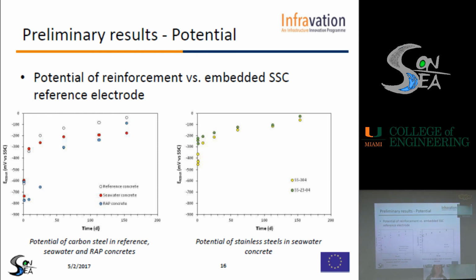On the left, the potential of carbon steel in reference seawater and RAP concrete, and on the right, the potential of the 2 types of stainless steel in seawater concrete. We can see that in all cases, the potential was rather low in the beginning, and then it showed an increasing trend. After about 5 months, we can see that all the potentials are quite high, and in particular, all